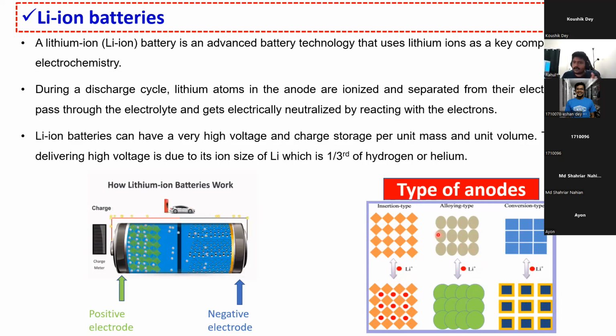And there is another type, alloying type, that's basically followed by silicon as well as tin-based materials, where the lithium will make an alloy with these compounds, and then the chemical reaction occurs. And conversion type is the mechanism happening with transition metal oxide, metal phosphate, metal sulfate based materials, where the lithium will react with that and get converted to another compound. Most commonly and widely people use insertion type of materials, because alloying and conversion types have their own demerits, like heavy volume expansion during charging and discharging.